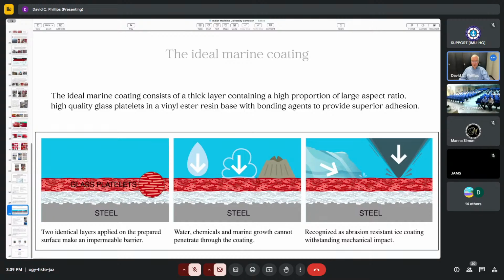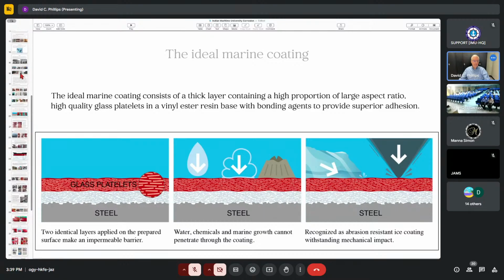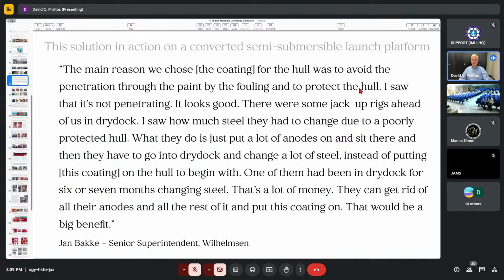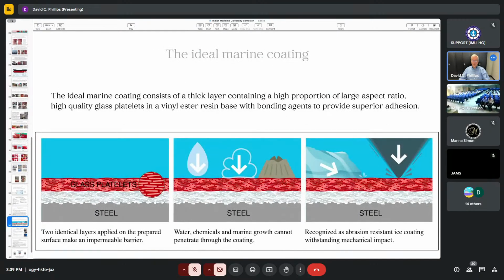Biofouling will attach, but it sits on the surface. It does not penetrate. Remember with this chap here, the rocket launch guy, he said the main reason we chose the coating for the hull was to avoid the penetration through the paint by the fouling, because barnacles do, they chew through. This coating, they cannot chew through. They don't like it very much, but they will attach. And if you can clean them off, you can clean them off without leaving a trace. You can clean them off without damaging the coating at all. And because this coating is completely non-toxic, you can clean underwater without putting chemicals into the water, into the marine environment. So the environment's becoming more and more important, including the underwater environment. Many people, many ports are very sensitive to what goes into their water.